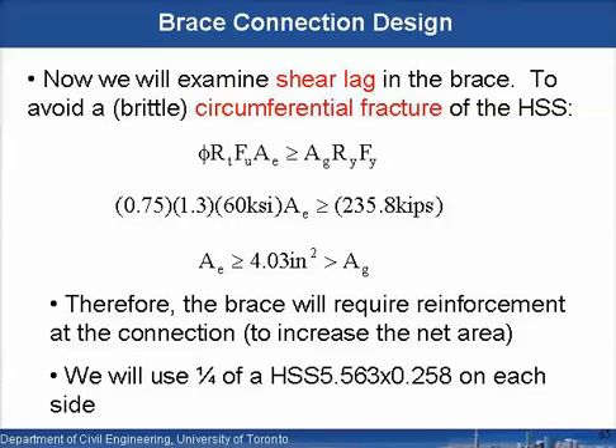Now we have to worry about the shear lag problem in the brace. Remember, that was the left-hand picture of those two, whereby we got circumferential fracture around the hollow structural section. This is essentially a brittle connection failure mode, which we want to avoid as well. So the strength of the connection for this particular failure mode must be greater than the actual ductile failure mechanism of yielding of the brace, with the overstrength factor again, the AgRyFy.